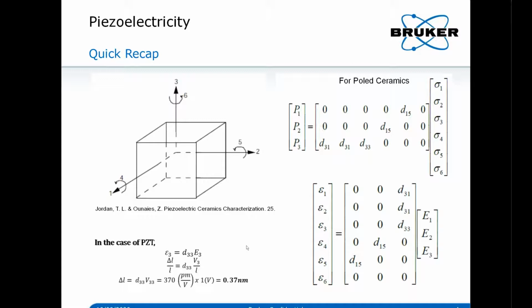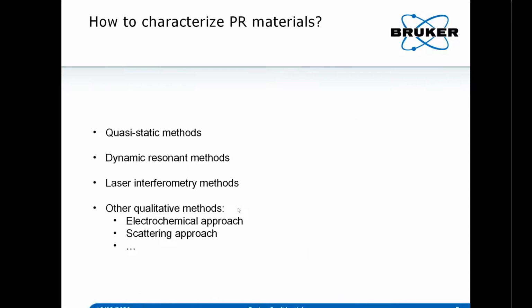Especially nowadays, when it's quite popular to have thin film piezo material applications, the response will be even lower. Let's take the example of PZT, which is considered a quite strong piezoelectric material. You just see the simple deduction here. If we consider D33 is 370 picometers per volt, and we apply 1 volt following the same direction, then the deformation is only about 3.7 angstroms, which means it's sub-nanometer. Such a small deformation can be quite difficult to detect, which poses a very important question.